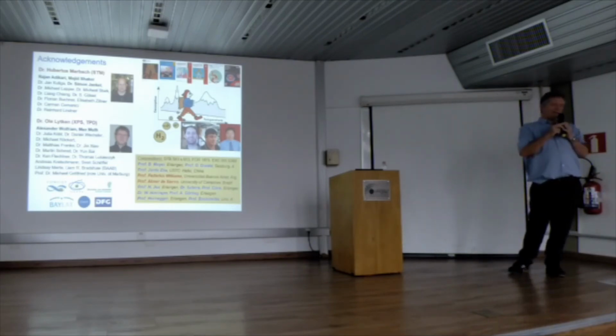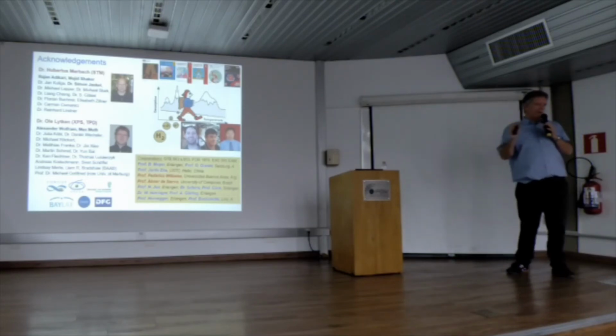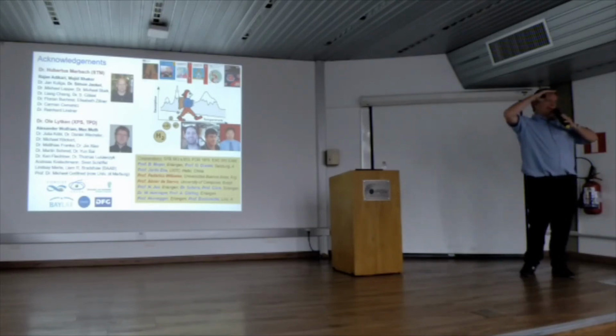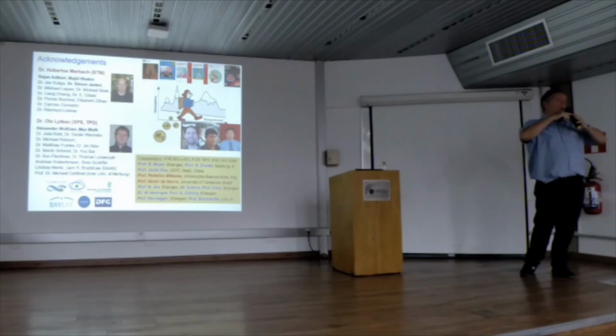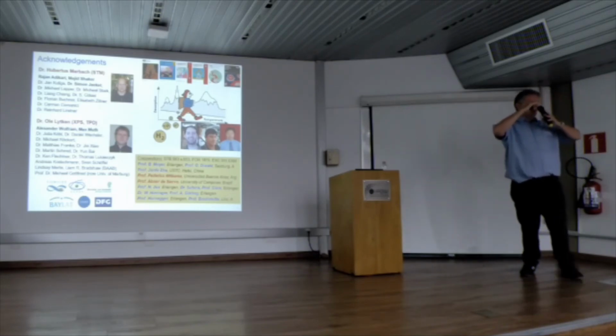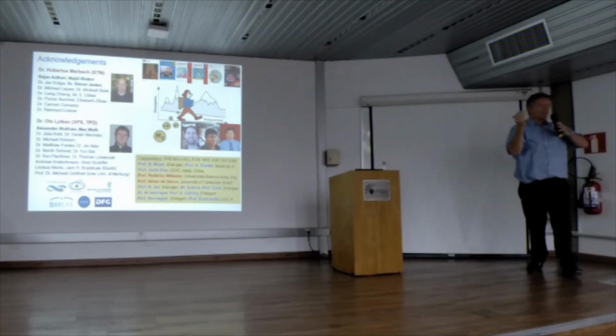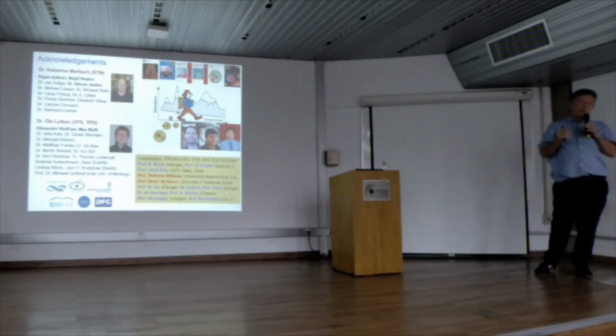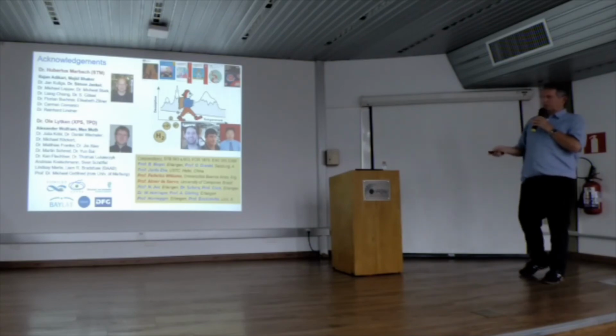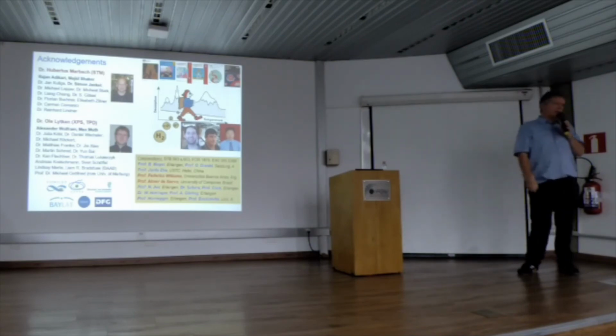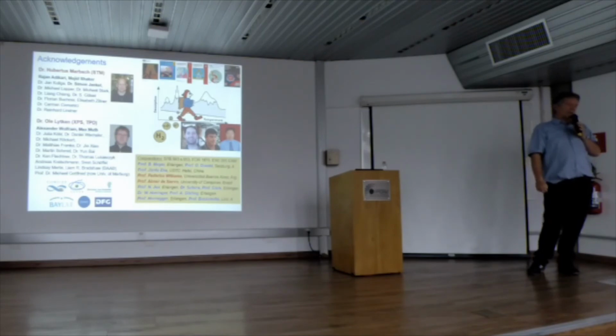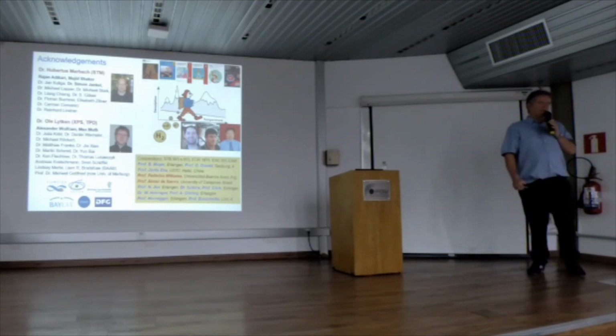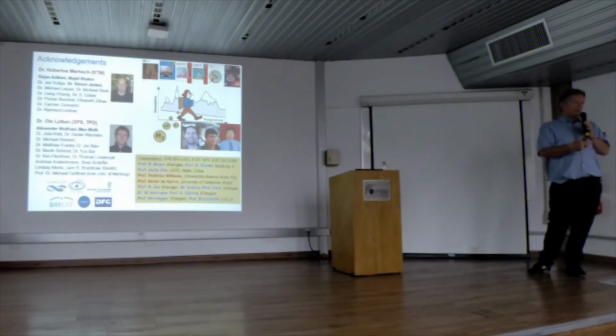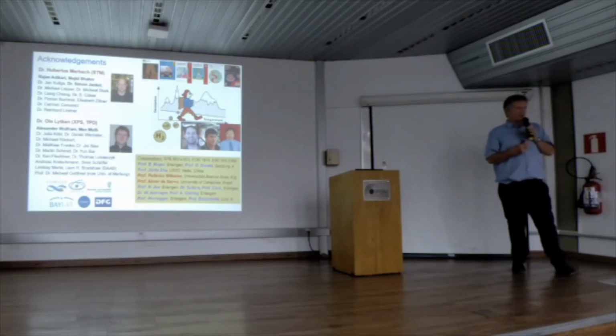But then the point we typically do not address here is what is the alignment of the levels of the molecule relative to the levels of the TiO2 for the charge transfer to be possible, but also not to lose too much of the energy, because you can fall down too far, and then this energy is lost. And so one important point that we also did quite extensively with Federico is, how can we bind the porphyrins to oxide surfaces with functional groups, like carboxylic acid, phosphonic acid, hydroxamic acid, boronic acid, and this is a topic that we follow up.